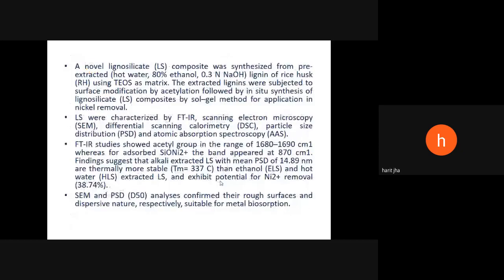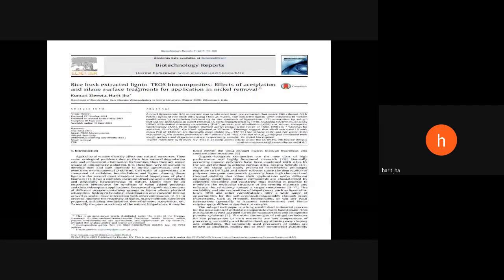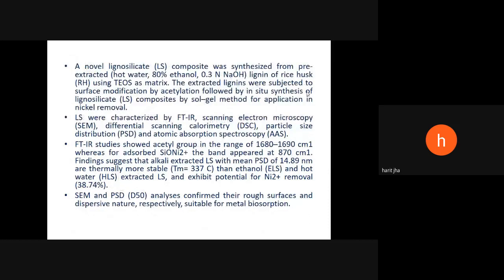In this work, a novel lignosilicate composite was synthesized from pre-extracted lignin of rice husk using TEOS as a matrix. In this we have used rice husk extracted lignin and TEOS biocomposite. The extracted lignin was subjected to surface modification by acetylation, followed by in situ synthesis of lignin silicate complex and composite by sol gel method for application in nickel removal. This lignosilicate was characterized by FTIR. As you remember, lignin not only forms complex with carbohydrate, it also forms complex with silica.